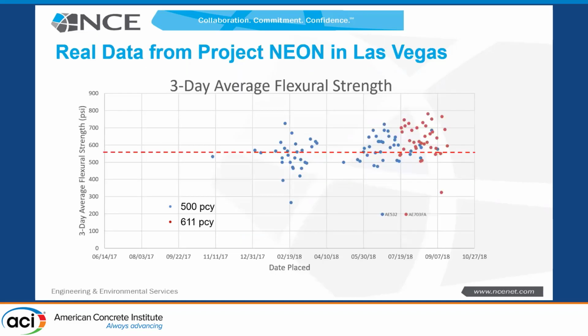I showed this one because this is a real project I worked on. This is Project Neon, Interstate Highway, I-15 through Vegas. We had a 500 pounds per cubic yard mix that got approved by the DOT through an ATC, another nice acronym. The minimum cement content requirement in Nevada to this day is 611 pounds per cubic yard. That's their minimum. We got them to accept 500 for this project.